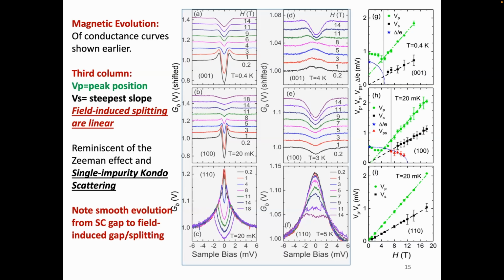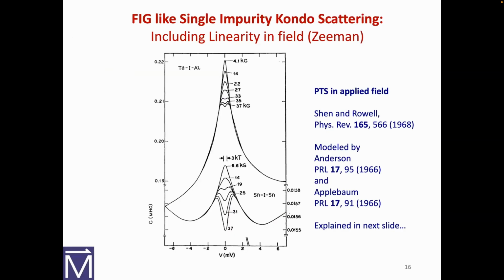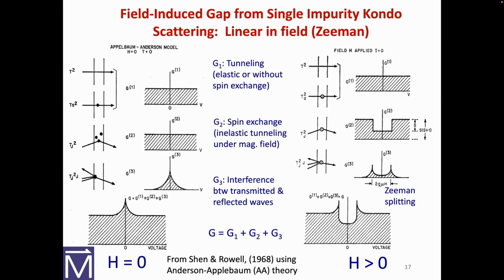Okay, but besides Zeeman splitting, that's also seen in single impurity Kondo scattering. So we're going to have a little leap of faith here. This is very old work, but my postdoc advisor was John Rowell, so I know all about it. Even before I was a postdoc, this is what I did with John Rowell. And what they were doing, not knowing, is this is not superconductivity. This is looking at planar tunneling with magnetic impurities either in the barrier or very near, just somewhere in the barrier. It can be in the center or near the surface. And what they found is that you get this splitting with applied magnetic field. And this was worked out by Anderson and Applebaum.